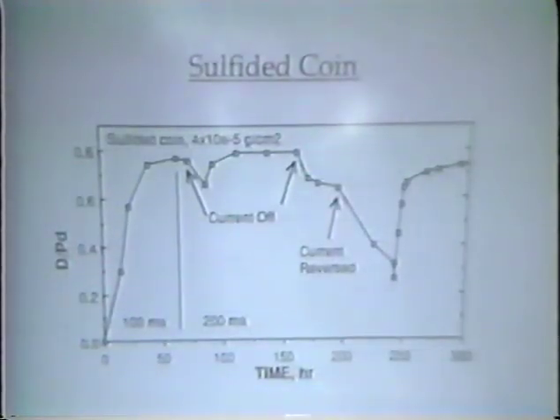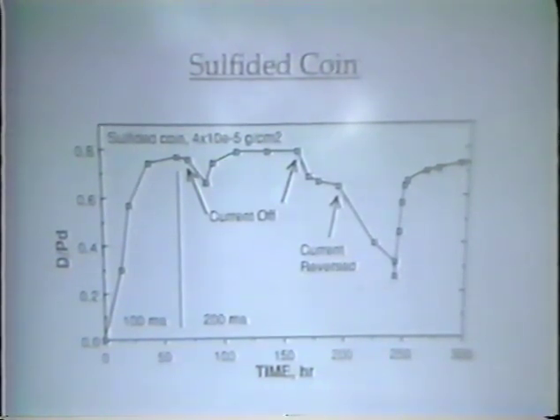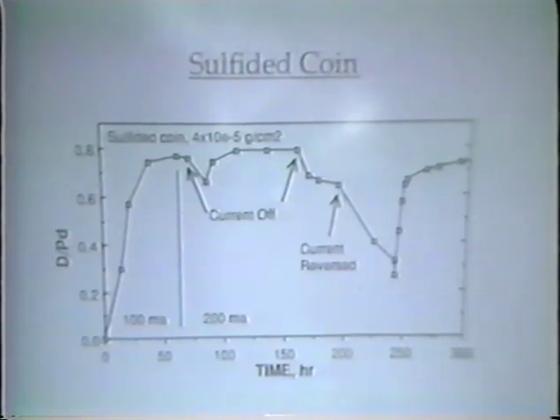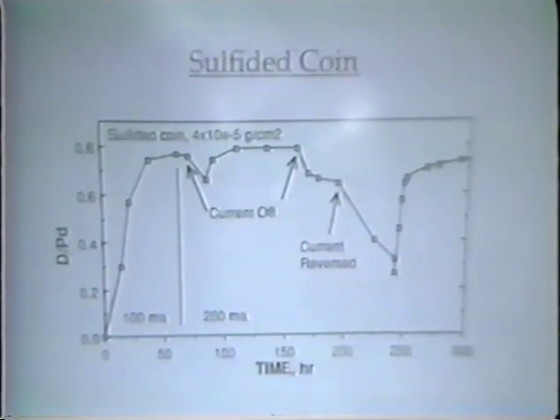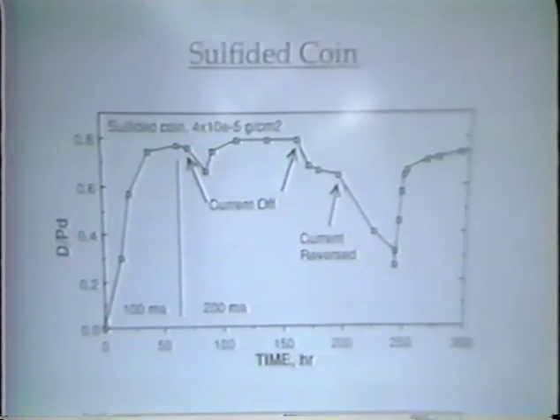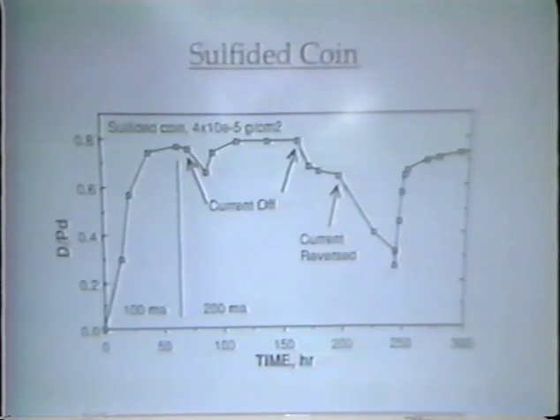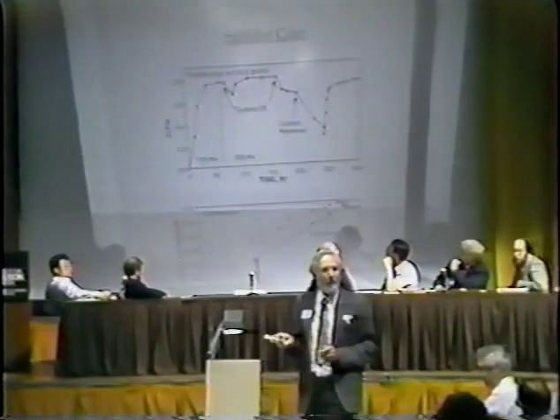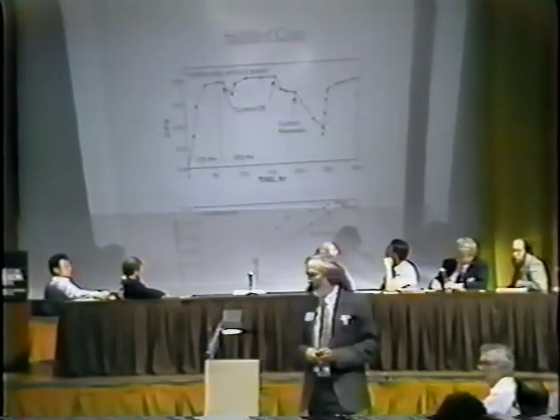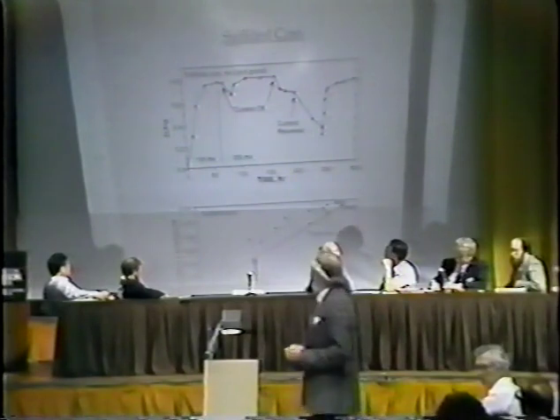We tried a number of poisons. Sulfur is known for quite a few years to be a good poison. Palladium, I might point out, has been looked at in a number of different ways. Some people like to have a catalytic surface, and other people want a poison surface. The people who want a poison surface are trying to get hydrogen in, and those have generally in the past been people who have been studying superconductivity, because this is a good superconductor at high stoichiometries. And so people have tried sulfur.